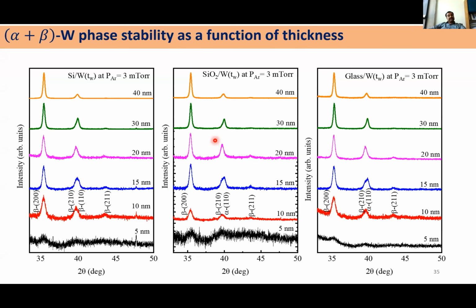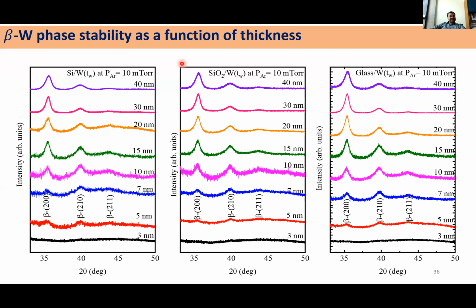Okay, and we wanted to see whether it truly depends on thickness. So basically you can clearly see that at 3 mTorr, okay, we deposited on 3 different substrates: glass, silicon dioxide, and silicon. In all the cases we get a mixed phase, irrespective of the thickness. And the interesting thing is this one, that at 10 mTorr, that is at a higher pressure, even at 7, 10, 15 nanometer, or even up to 40 nanometer, you can stabilize pure beta phase by varying the sputtering pressure. So that tells us that you can have a pure beta phase above 5 nanometer.